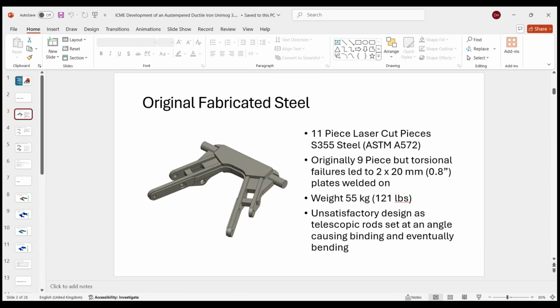When it was first designed, the design was obviously very simplistic, a metal fabrication made up of 9 pieces of steel. When they put that into the field and lifted up some wood chippers, they found that there was too much load on the part and they were starting to fail. So they added some additional pieces of steel into an 11-part component, weighing 55 kilograms, and it did the job in a manner, but it looked pretty awful.